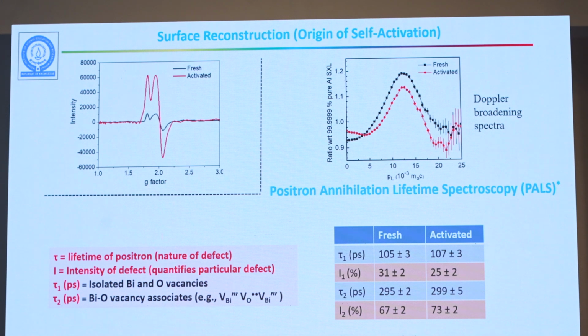A little bit more detail: when you remove one oxygen, it becomes positively charged. If you remove one metal, it becomes negatively charged. Our surface is negatively charged. Our data shows that it is negatively charged, which means that more zinc and bismuth has come out from the surface. Now, this is positron annihilation spectroscopy, in which you use positrons, and a positron hits your material and reacts with the negative charges on the catalyst surface. If you look at how these positrons decay, because they are neutralized by the negative charge, you can figure out what kind of defects these materials have.